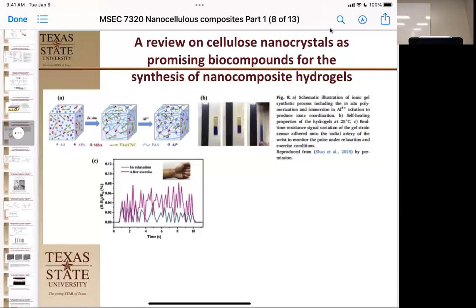Okay, so in this example, they were trying to make some cool biosensors. And what they wanted to see was, can we detect heart rate using a flexible biosensor that's glued to the skin? So they're looking for that bump, changing the electrical conductivity. If you look here, this is the ratio of the resistance without a stress and with a stress. And this dark line right here is in the relaxation. They see some signals that are associated with the relaxation, and during exercise, they seem to be sensing something.